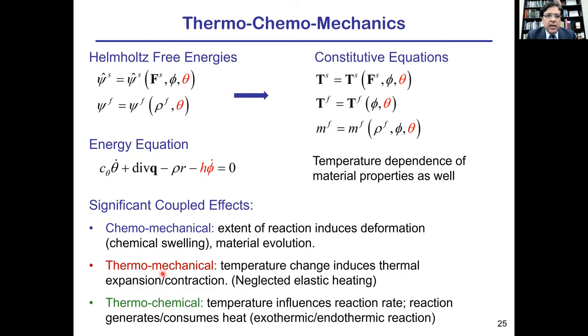We are now extending it to thermomechanical problems for which we need to write the Helmholtz free energy function as a function of the temperature field. This gives rise to constitutive equations where the Cauchy stress for the solid and the fluid is also temperature dependent. In addition, the mass conversion rates are also temperature dependent. So we need to solve for an energy equation. We need to add this energy equation to the balance laws for the fluid and for the solid. And this gives rise to significant coupling effects.